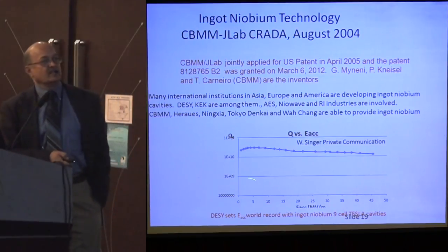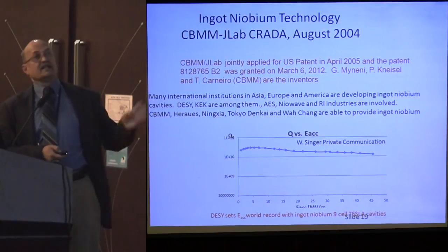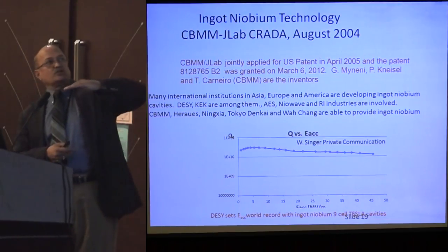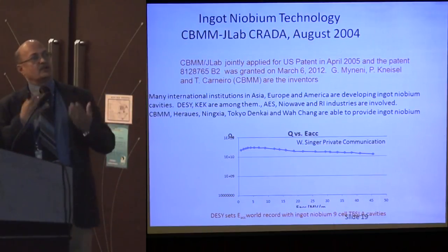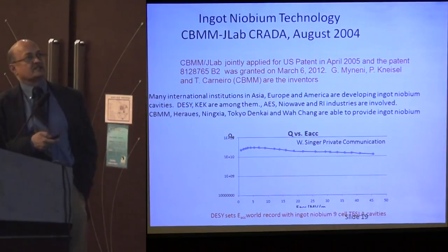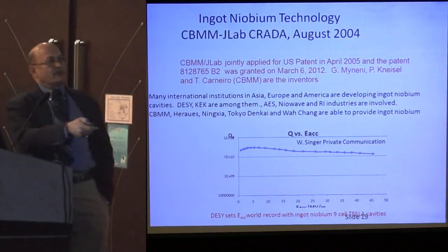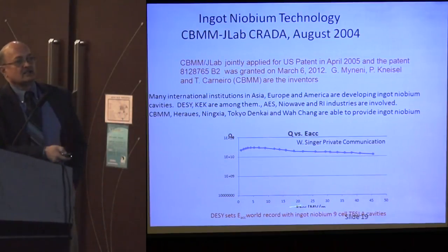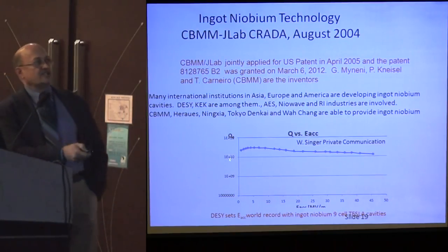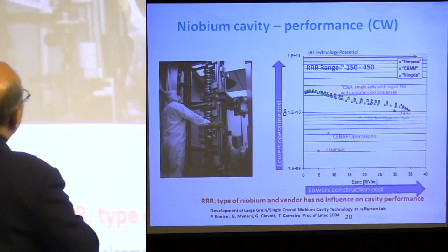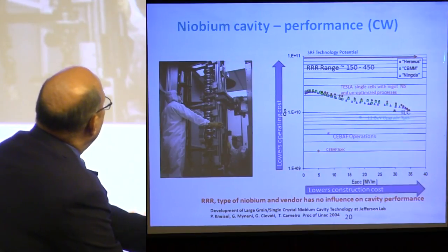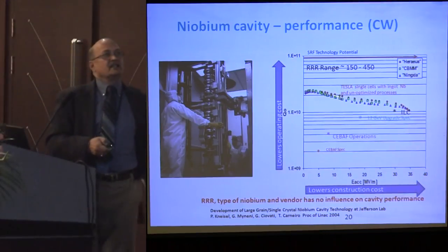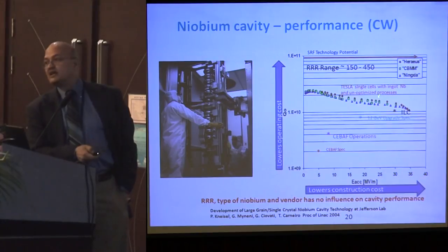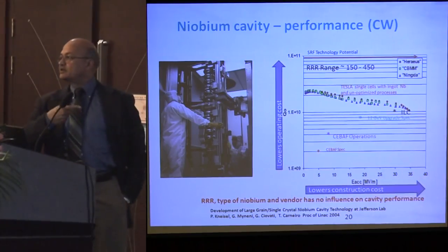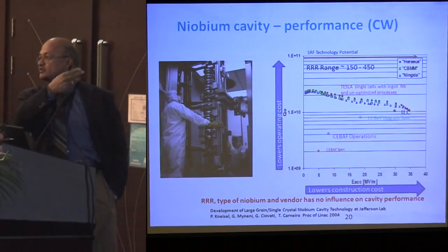During that process, we reinvented what we call ingot niobium technology. The ingot niobium is sliced into sheets and they are formed into cavities. With that process, the cost could be very much reduced and the performance is also pretty high. This is the accelerating gradient here and the quality factor. You want this to be very high. This shows the comparison of different materials, with the RRRs ranging from 150 to 450 from three different vendors. Basically, the performance of the niobium single-cell cavities is identical, but the cost difference of the material is potentially a factor of three, depending on which vendor you use.